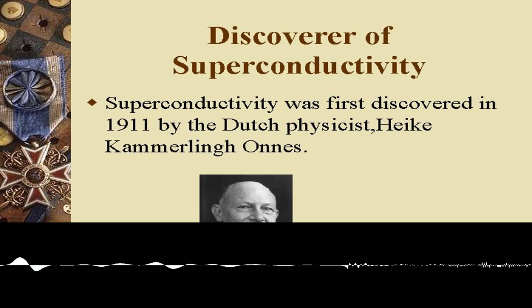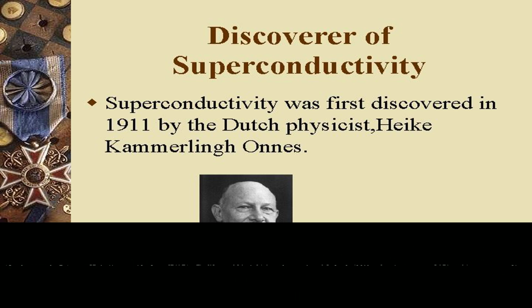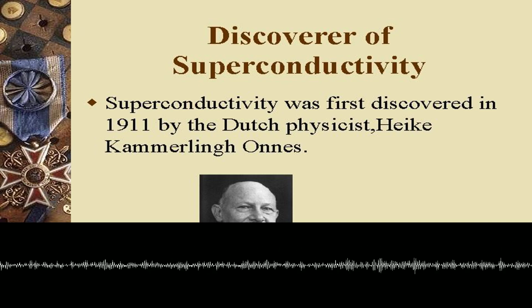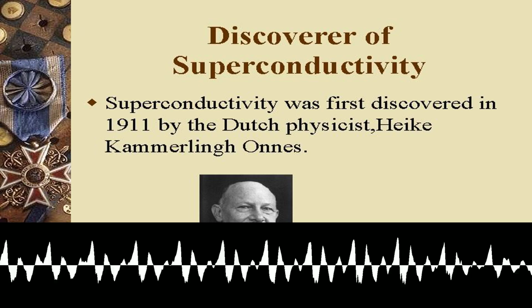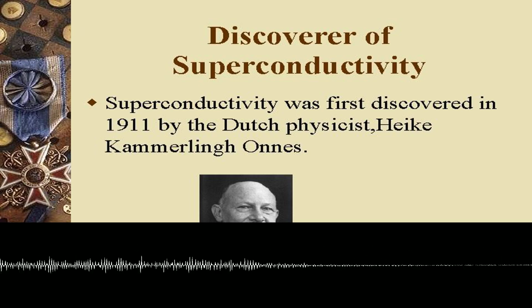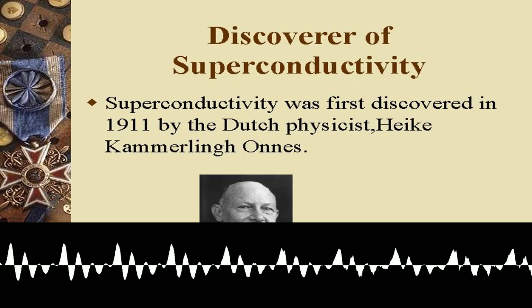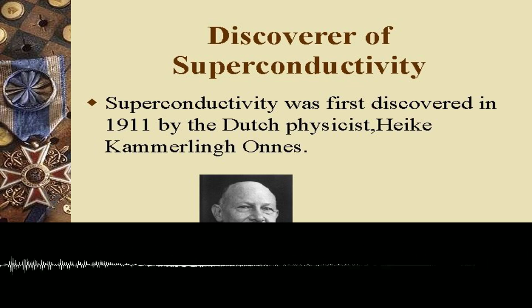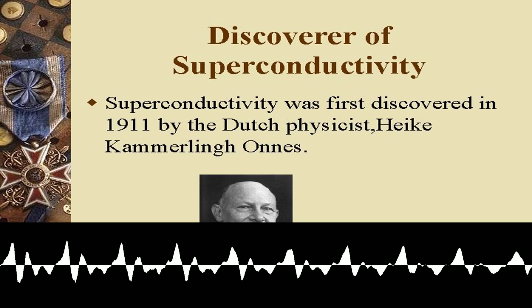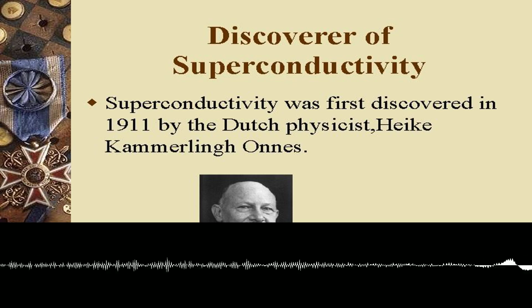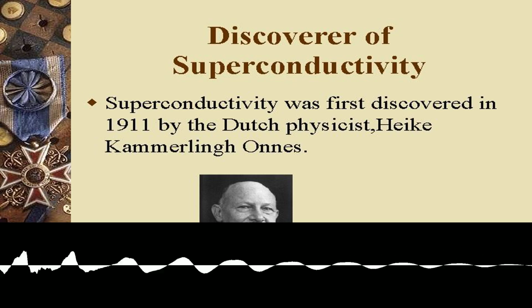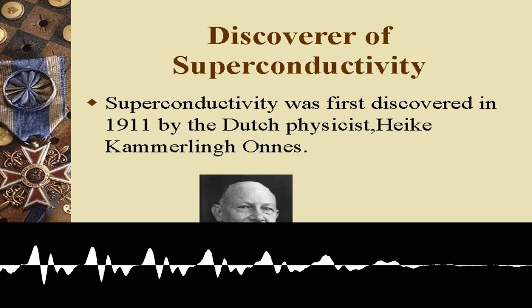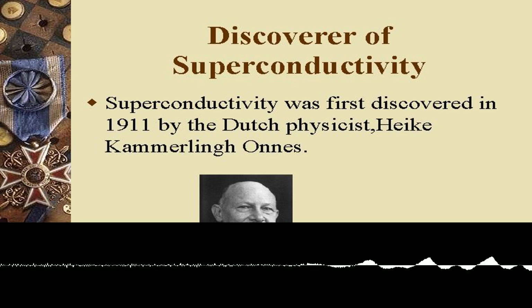This led to the central claim that superconductivity is a distinct state of matter defined by a precise critical temperature, which they denoted T_c. Their analysis presented this transition as exceptionally sharp for a pure, strain-free sample like their mercury thread. The internal evidence for this claim came from experiments where they varied the temperature in tiny increments around the transition point, observing that the entire resistance drop occurred within a window of a few hundredths of a Kelvin.